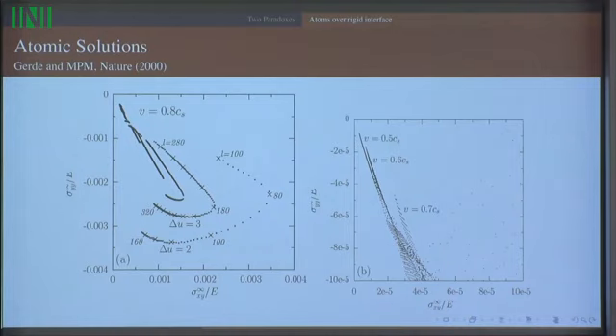This is a close-up on all the little bubbles we found running at 8/10 of the shear wave speed. And then this is an overview of lots and lots and lots of little bubbles that we found. Every dot here represents the solution of 2 Wiener-Hopf matrix factorizations plus their joining to a continuum solution. I'll describe that in a second.